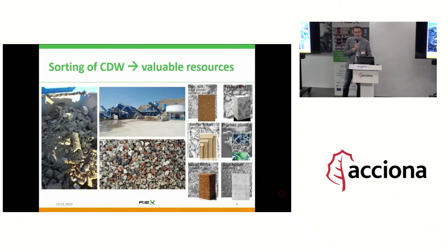So all of these rely, to achieve these high replacement levels, on good sorting, good separation of CDW to receive clean fractions. As you see here, to the left, you have incoming CDW. In the middle, you have a typical recycling plant from CDE, our partner in crime. And to the right, you see ideal fractions, different material fractions that you can use for different types of things. For example, wood fiber fraction, which can be used for insulating panels, or aggregate or mineral fraction, which can be used as new aggregates in different types of concrete.